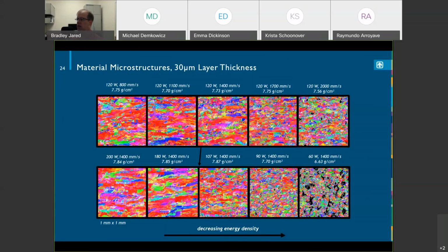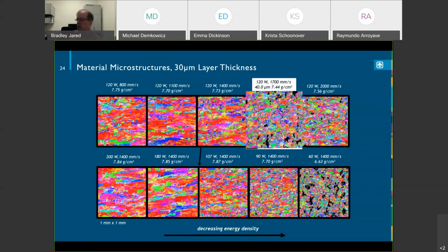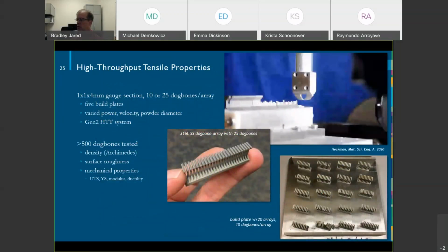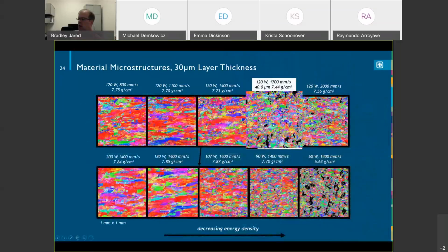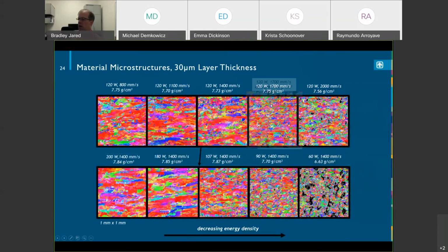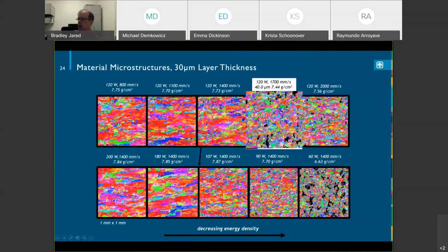Let's see. Oh yeah. So this is showing the settings, 120 watts. This shows what happens if you just change the powder layer by 10 microns. Sorry, went the wrong way. So this is 30 micron, with a 10 micron change, and you see a dramatic increase in porosity and a reduction in the microstructure, the grain size. These are all things a lot of people don't always think about, layer thickness. They just think it's 30 microns. Well, it's not really. It's a variation. So these are all things that probably introduce a lot of the variability we see in the processes in some cases.